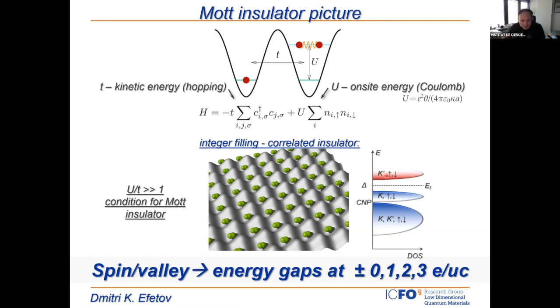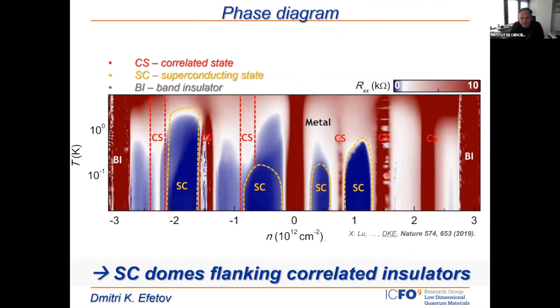And then the other thing, of course, which was very striking, and was observed in the very beginning by Pablo, was that when you look at the temperature dependence of these resistance measurements, there are also regions where resistance just drops to zero. And this is shown here. Red are regions of high resistance and blue are regions of low resistance. The insulators I talked about a second ago are these red regions. And you can see flanking these red regions, there are a lot of blue regions where superconducting domes are observed.